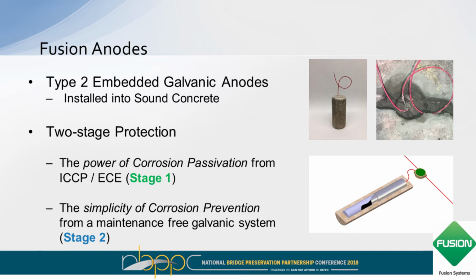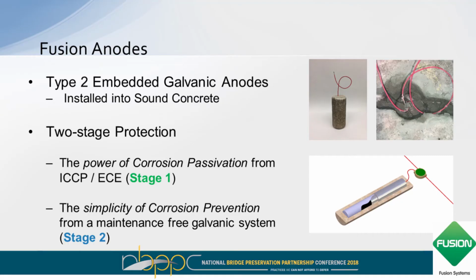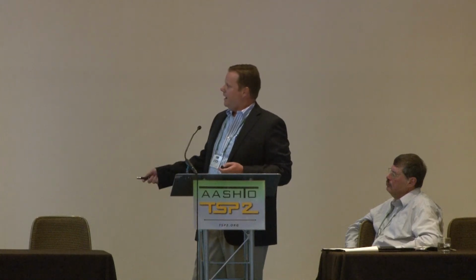You get passivation from the initial phase, it's like the chloride extraction process. You want to put enough current to the steel to passivate the steel. And then after that happens, it automatically switches from an impressed current phase to a galvanic cathodic prevention phase. So it becomes more of a maintenance-free option. That happens automatically. You don't have to turn the system on, have a rectifier, then come back at a different time. So from a construction standpoint, it might be something to look at.